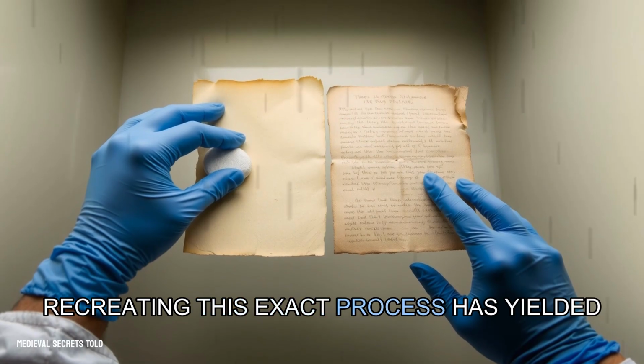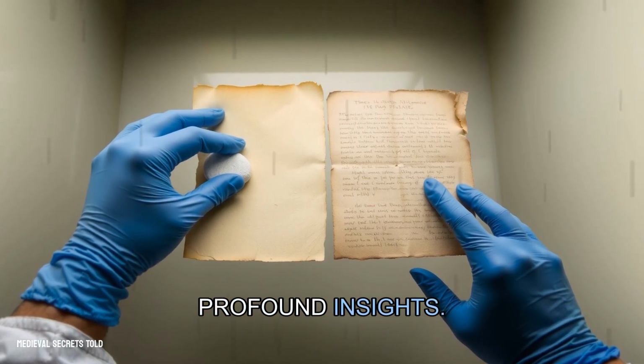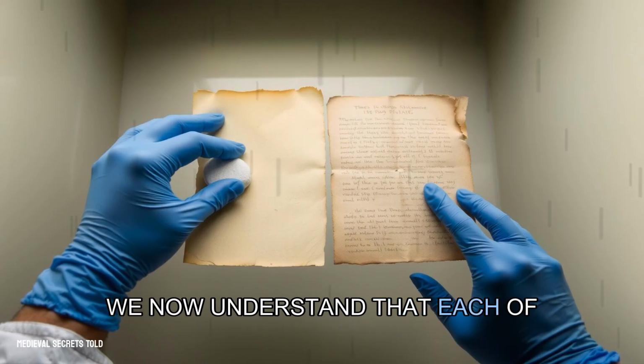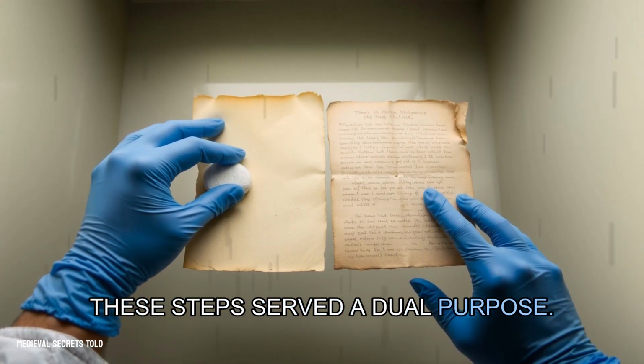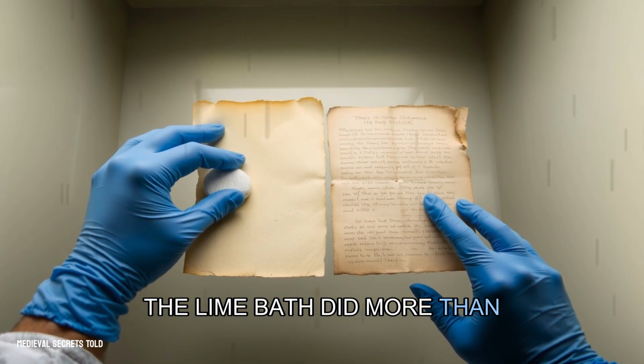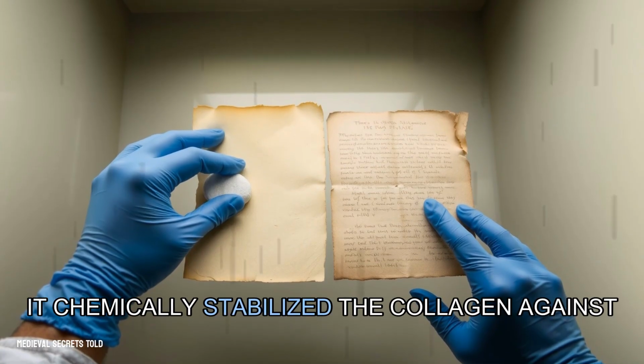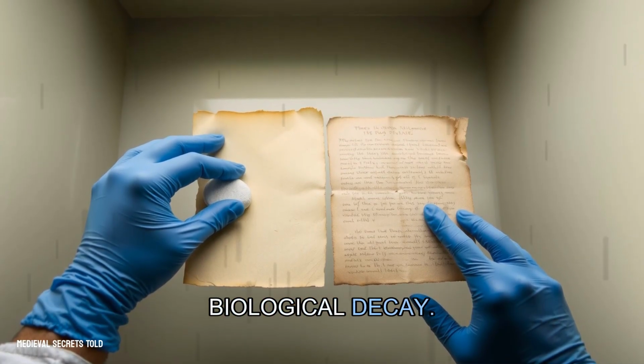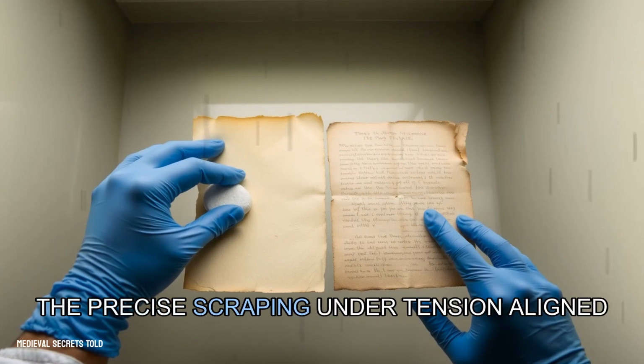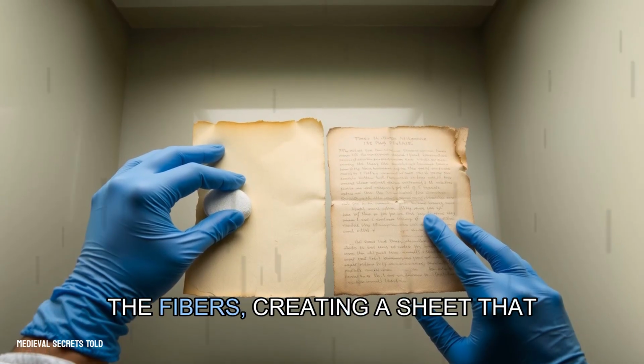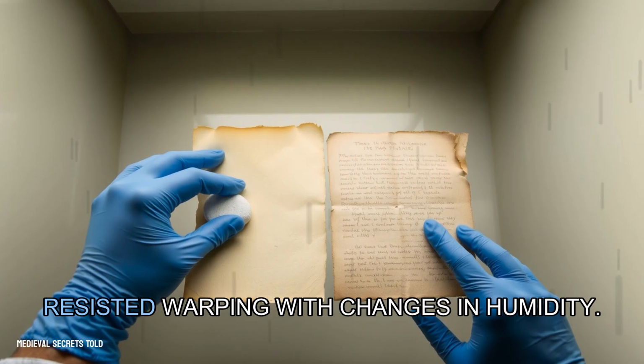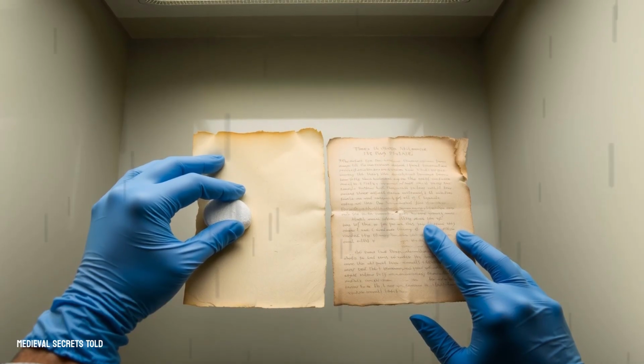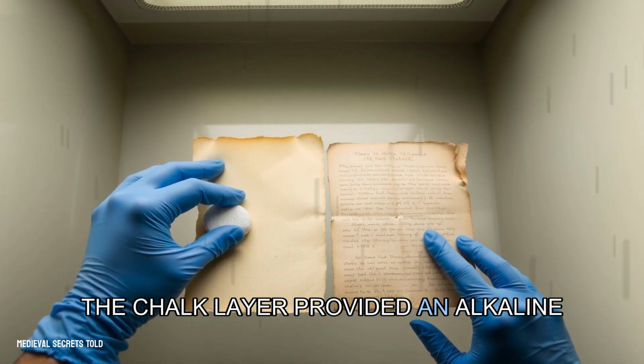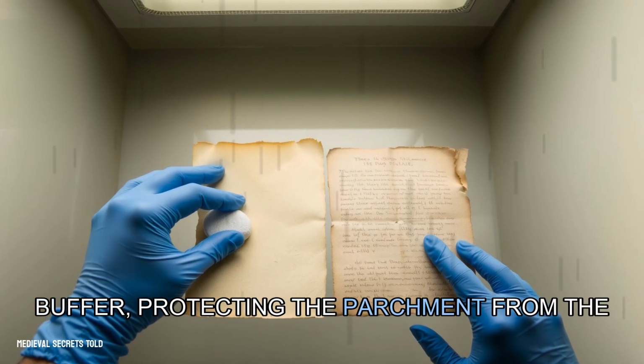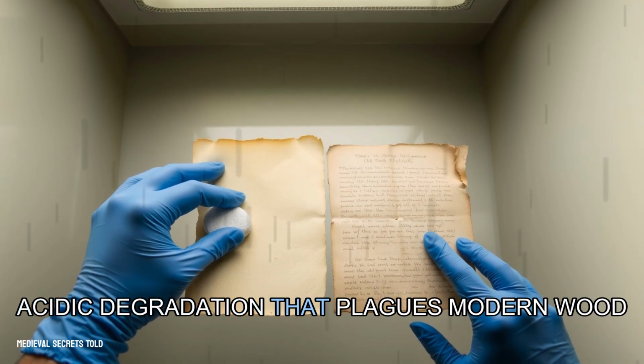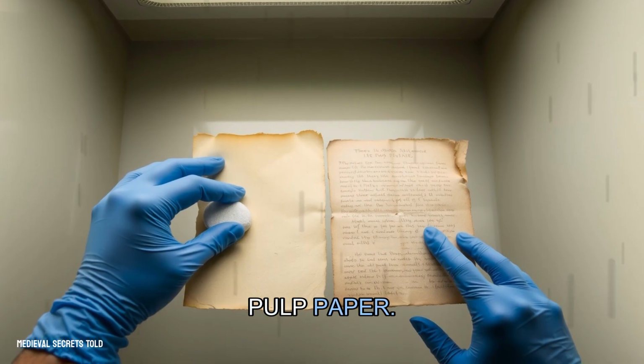Recreating this exact process has yielded profound insights. We now understand that each of these steps served a dual purpose. The lime bath did more than clean, it chemically stabilized the collagen against biological decay. The precise scraping under tension aligned the fibers, creating a sheet that resisted warping with changes in humidity. The chalk layer provided an alkaline buffer, protecting the parchment from the acidic degradation that plagues modern wood pulp paper.